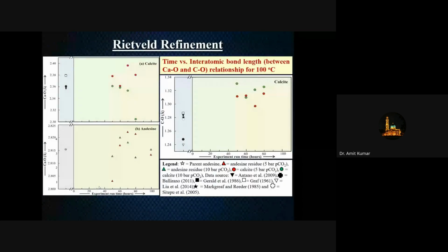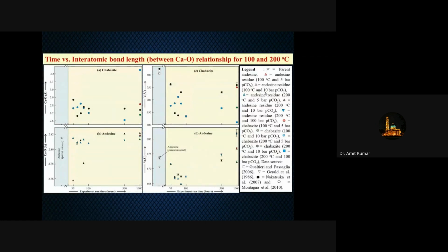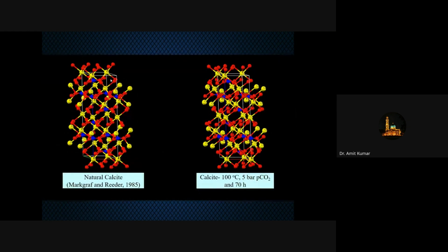Besides this, we did the Rietveld refinement also to determine the crystallographic growth of these secondary minerals. For example, the calcium-oxygen bond length increased in the case of 5 bar PCO2, pressure of CO2, and in the case of the carbon-oxygen bond length, the growth rate was more or less similar to the previous one. After that, the zeolite mineral chabazite, a calcium zeolite mineral, formed from the andesine mineral. Andesine is the primary mineral, and chabazite is the secondary mineral, which was formed due to the carbon sequestration experiment. After that, we compared the natural calcite mineral with the experimentally formed calcite mineral, and they are identical to each other. So we can conclude that such secondary minerals can also be used for industrial purposes, because they are crystallographically identical to each other.